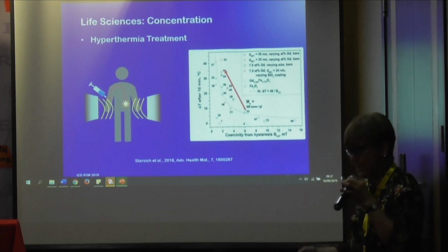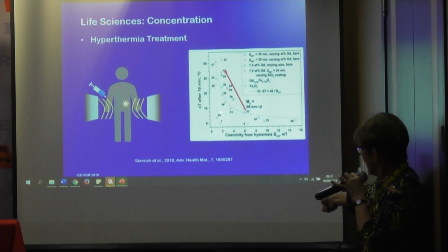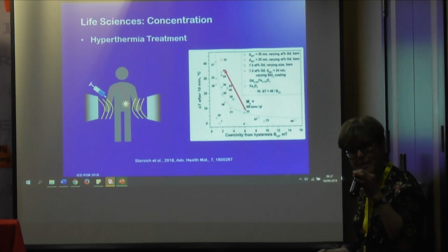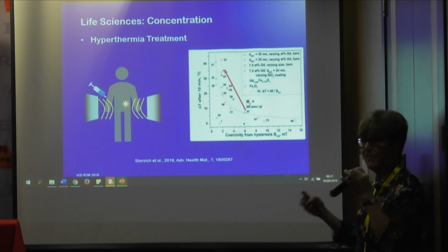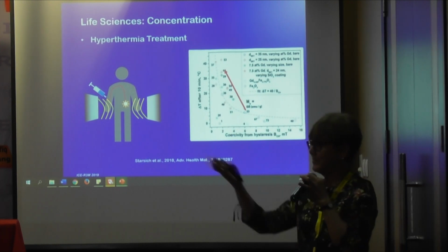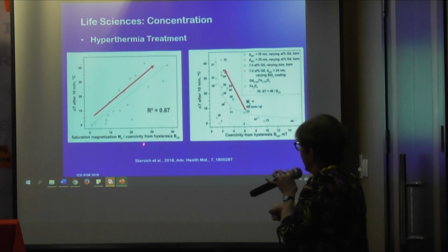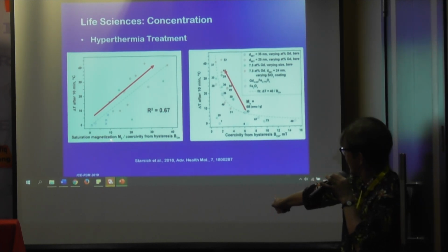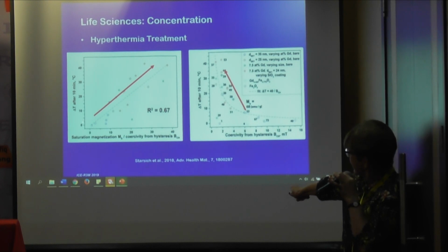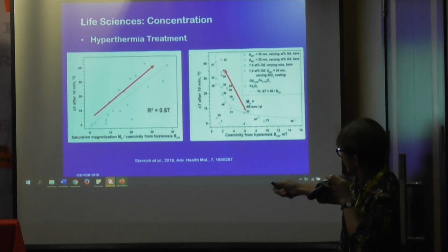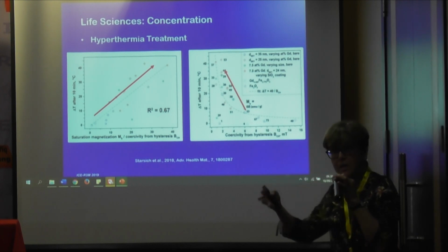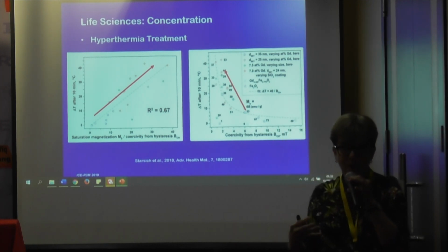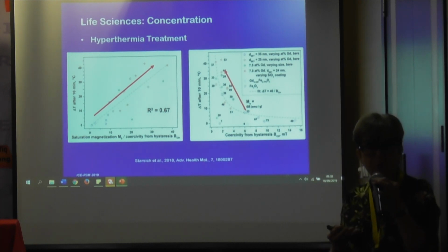So what he found was that these particles here had a very low saturation magnetization, whereas these particles here had a very high saturation magnetization. And so he developed this parameter where he took saturation magnetization divided by coercivity. So if coercivity goes to 0, this value will become high. And he found a nice linear relationship between the rise in temperature and this parameter. So this they now use as a guide for how well the material would behave, okay?